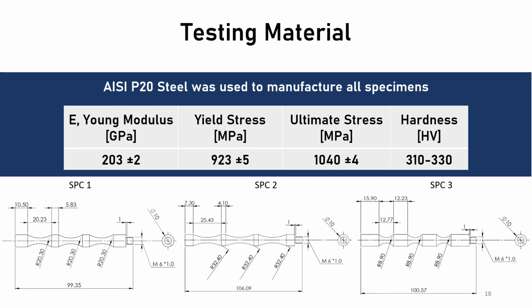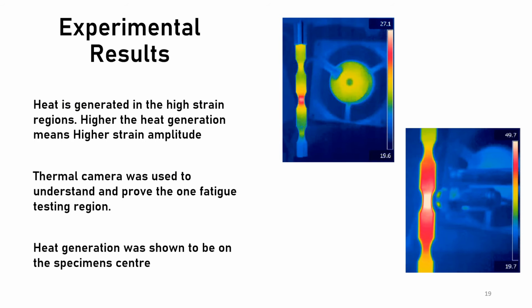Now, using the basic mechanical properties of the AISI P20 steel applied in this study, we designed 3 different multi-axial specimens. Looking at the experimental results, we first conduct a thermal analysis on all created specimens. Because in ultrasonic fatigue machines high strain rates are applied, a high heat generation occurs in high deformation regions. So, by having a high heat generation at the main throat, we prove that we have a higher stress combination in the main throat, the fatigue testing region.